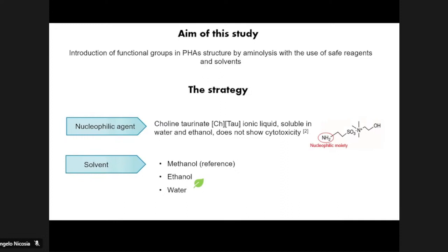The use of choline taurinate leads to the introduction of a sulfonic polar group in the PHA structure and to an increase in their wettability. Additionally, aminolysis usually is carried out in methanol, so we used it just as a reference, with the aim to replace it with ethanol and water, which are considered green solvents.